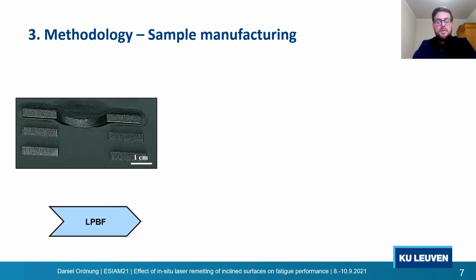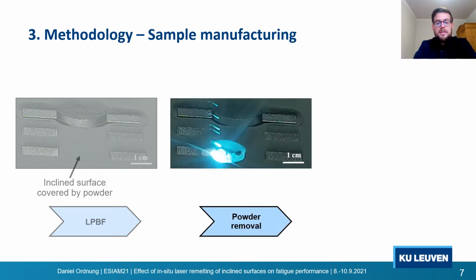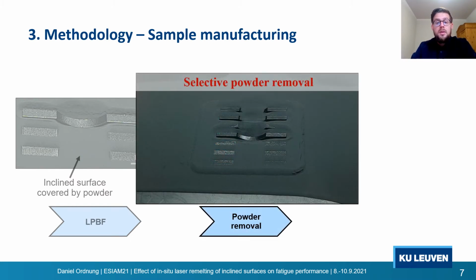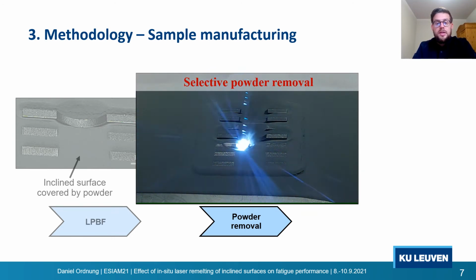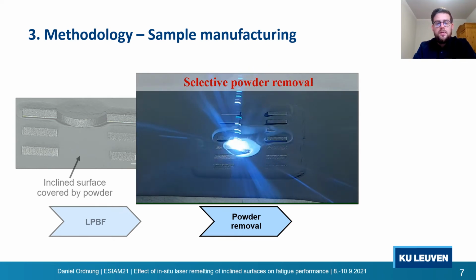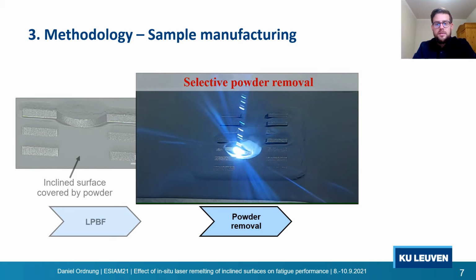The fatigue samples were manufactured by laser powder bed fusion, and after building, the inclined surfaces are covered by powder, and therefore it's not possible to laser remelt them. Thus, we applied the powder removal process, which is illustrated here in the video. So you can see the pulsed wave laser starts to scan the top surface, and by a reaction, shock waves are created. These shock waves interfere with the powder bed and blow away the powder from the inclined surface.